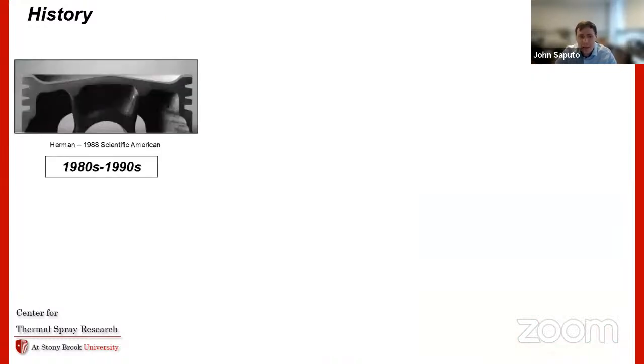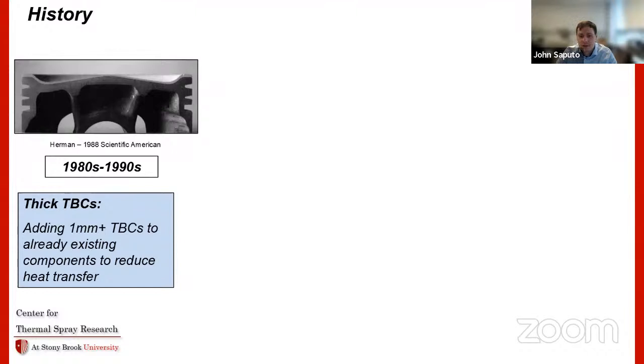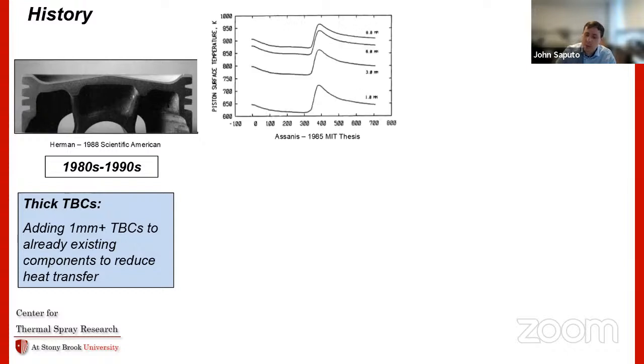So in the 80s and 90s, you see people start to look at these things and try to actually gain performance benefits by insulation. The idea in this time was to use coatings on the order of 1 millimeter thick, just added onto existing components to try and reduce heat transfer. What you see is something that happens like this. This is the surface temperature of a piston versus different crank angles. You can think of this just as different times during the combustion process. And as you go from a thinner to a thicker coating, you're moving from the bottom to the top line.